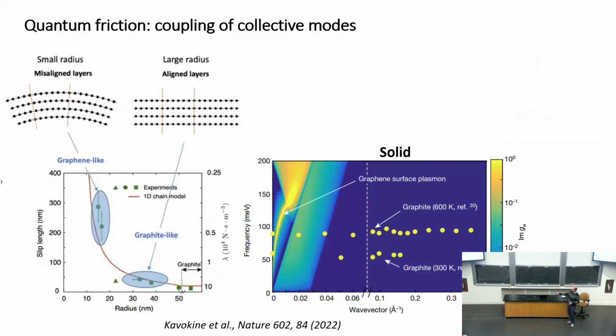So as a result, if you look at these experiments here, which were done on multi-wall tubes in large radii, where these tubes look like graphite stacked, you have these surface plasmon modes, which the water can dissipate momentum very efficiently. So there's high friction here, versus at low radius, when you have curvature, you start to decouple the sheets electronically, and your friction goes down.